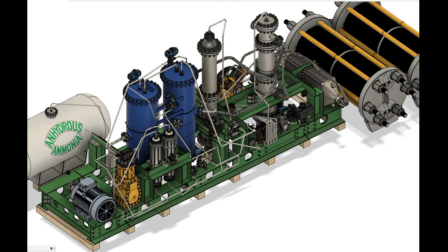The diaphragm sheets are subject to intense fatigue stresses, due to the cumulative stress of the sheet bending on the perimeter of its mounting flange, hundreds of cycles per minute. The diaphragm sheets eventually fail right on the outskirts of the flange clamping location of the diaphragm head. Failure usually begins with microcracks, which gradually grow to major fissures, necessitating the replacement of the unit. If left unchecked, a rupture can cause oil and gas to mix and subsequent downstream contamination if warning sensors are not installed or fail to alert the user.